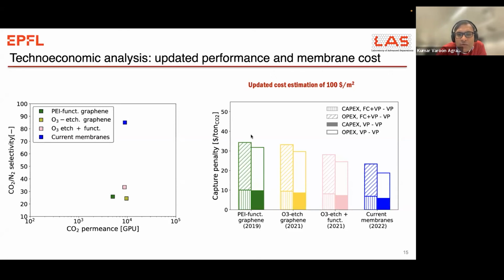And once we do that, we could say, if we scale up these membranes to a large area, the capture penalty of CO2 can be quite attractive. So already in 2019, which is our first generation membrane, these were about $30 to $40 per ton of CO2. That's the capture penalty, and now we are below $30 per ton. And why are these numbers important?